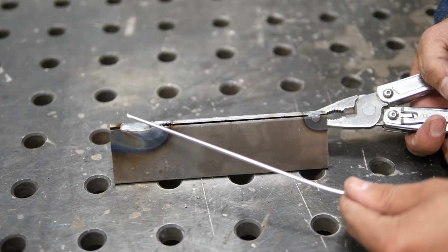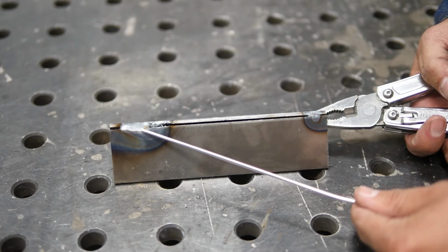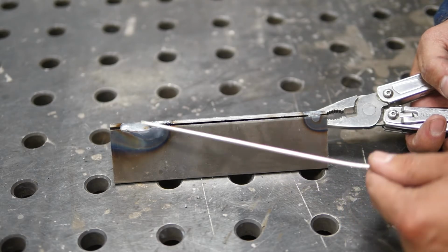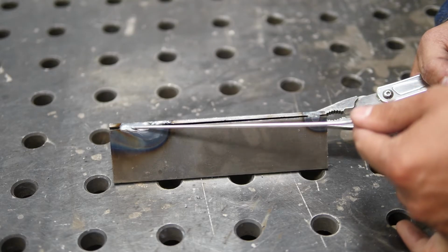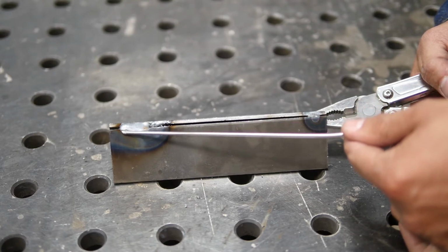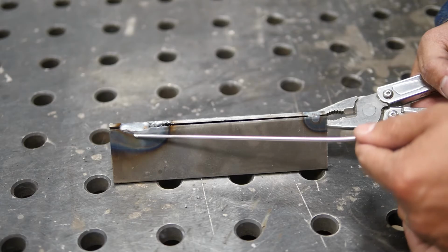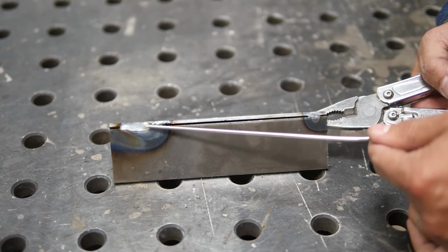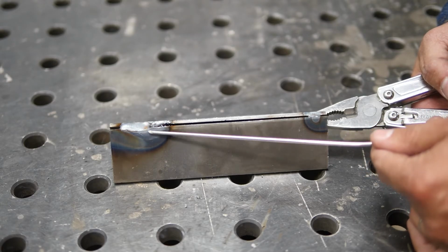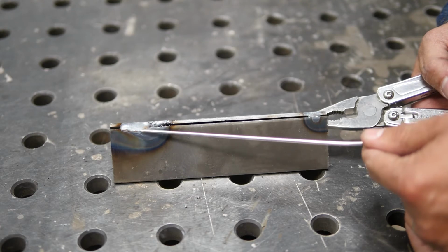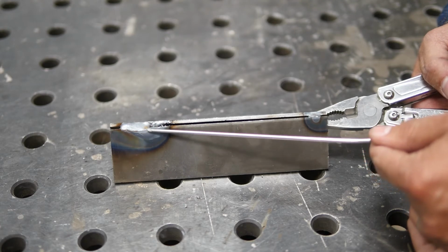And there it is, you can see it, 240 inches per minute, which was fine on our other weld, but here it blew through only after about 1 inch of weld. You can really see that material start to sink down lower into the plate. This is how I know as a welder I need to turn my wire feed speed down when I really start to see this weld get out of control.